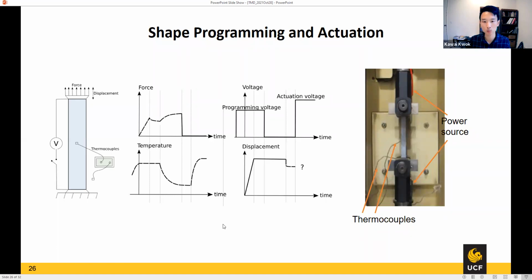But we really would like to be able to track that over time, and with all of these properties, the temperature and the force applied and the voltage are changing. Are we able to track that over time precisely? And so we have electrothermal mechanical models, so we have the electrical input, how the heat conducts into the polymer, and we have a mechanical model for the polymer deformation. This is an experiment we run in conjunction with the model we are doing. Obviously we want to predict the displacement by varying different programming cycles.